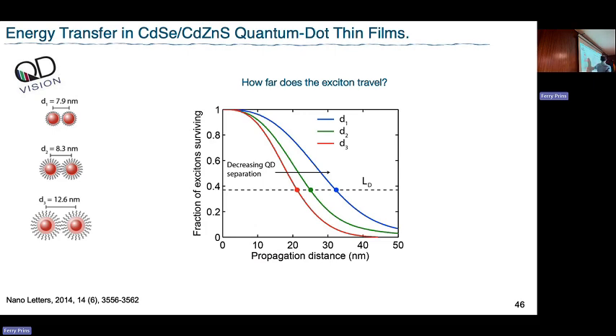You see that indeed you are increasing the diffusion length as you are decreasing the distance between the particles. This is an important parameter you advise on. Also here, propagation distance is just tens of nanometers. This shows you the power of this technique, that we are able to resolve the diffusion of particles which are diffusing only some tens of nanometers.